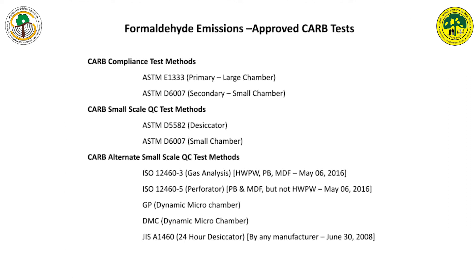It is important to note that the CARB panel has approved the gas analysis or desiccator method for hardwood plywood. The JIS desiccator method is approved for all manufactured wood composites. However, a 2016 approval letter indicates that the perforator test for production quality control is approved only for particle boards and MDF. Therefore, we may need to think of a universal production quality control standard acceptable worldwide to avoid confusion about which test applies to which type of wood composite.